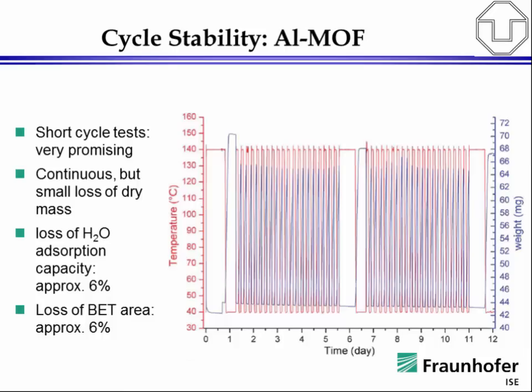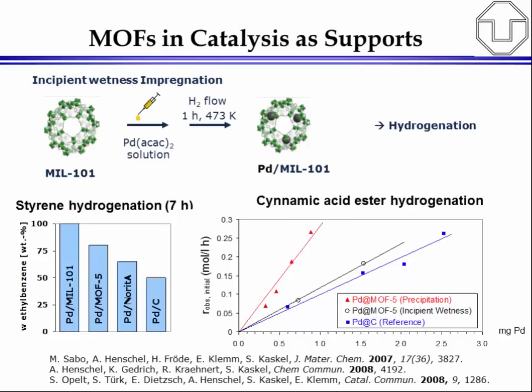So I will further go on in the next slide with some other applications or potential applications, for example, MOFs in catalysis. I should say that there's a wide variety of research results in this area already, also by other contributors. We have relatively early used metal organic frameworks as supports for metals. Also the Fischer Group has done this using some other methods, but here we show, for example, early results on using a MIL-101 structure, where you very easily can use an incipient wetness impregnation to generate palladium or platinum particles inside the porous system.